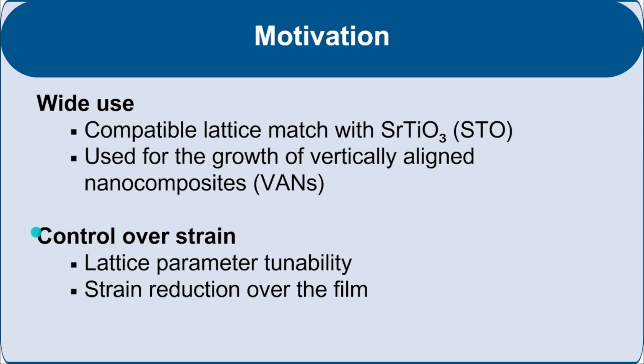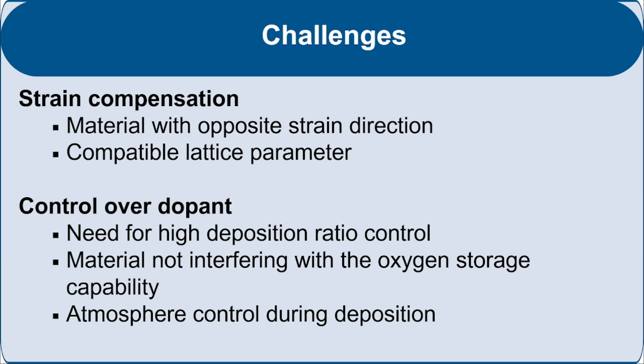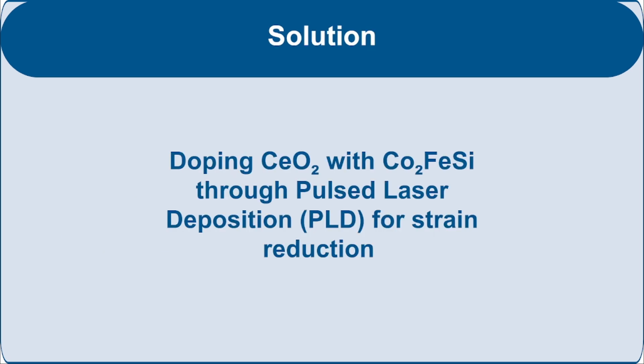In the growth of VANs, the control over the lattice parameter and planar strain is essential for the success of the formation of the desired structures. However, one of the challenges is selecting the appropriate dopant, one that could effectively reduce the strain in the CeO2 film while also offering precise control over the deposition ratio as well as not interfering with CeO2 oxygen storage capabilities. We investigated a broad range of elements and compounds before selecting Co2 iron silicon, or CFS, as the optimal dopant for our CeO2 films. We chose PLD due to its great control over the deposition ratio of the materials in the technique.